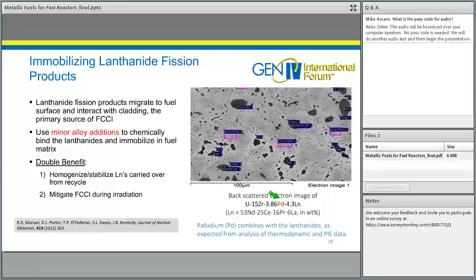One of the early ones we looked at was palladium. And so here you see not irradiated fuel, but fuel being examined after casting studies. So we cast metallic fuels with the palladium added and with lanthanides or rare earths added as well, and then characterize the microstructure, what's happening to the lanthanides. In casting studies, we have found that the palladium and the lanthanides do in fact precipitate in phases together. So the palladium is reacting with the lanthanides and hopefully keeping them from transporting.